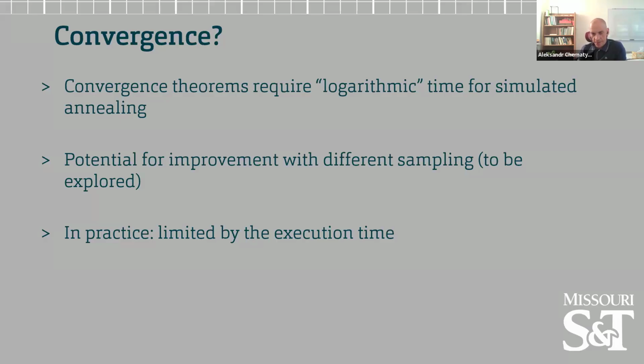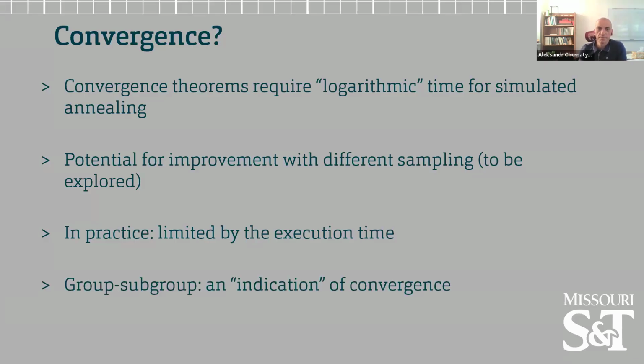As I already mentioned, in practice, we are really limited by the execution time. So for a typical simulation run for a given structure, by our experience with the hardware that we have, we can typically evaluate on the scale of 10,000 structures. So this is our limit for a given space group. This is our typical run, which will take us about a day or so to run. And if I want to sample a few different space groups, then one can correspondingly increase that number.